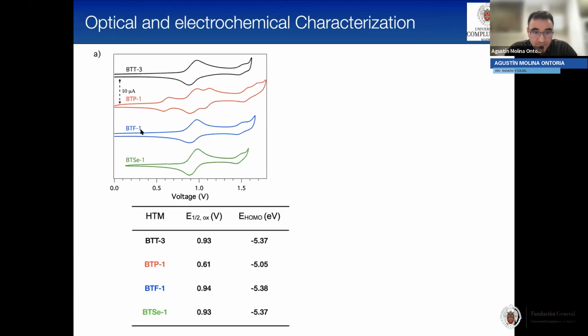From here, we can see that BTF-1 and BTSe-1 display only one oxidation wave, which is 3 simultaneous oxidation processes, one from each triphenylamine, for a HOMO energy of around minus 5.38, minus 5.4, more or less. And BTP has stronger electron donor properties, with a first oxidation wave cathodically shifted by around 0.3 volts. This corresponds to a HOMO energy level of minus 5.05.